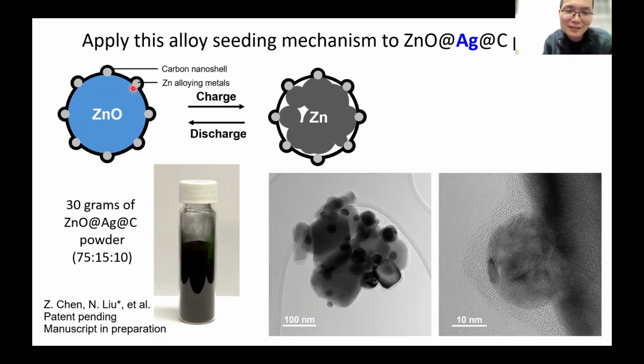That's the design here. And we can make a lot of particles and you can see them under the TEM. This is the zinc oxide, and then this silver nanoparticle, and the carbon is on the outermost. Right? You can see, in a higher magnification image, the carbon outside, silver, and the zinc oxide.